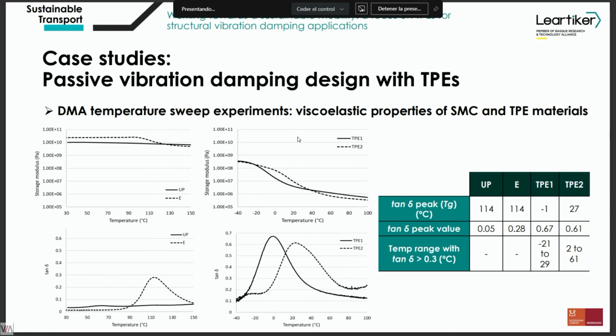On the other hand, if we compare the viscoelastic properties of the TPEs, we can see that the stiffness values are low, but the loss factor, tan delta, the vibration damping capability or energy dissipation that these materials give to the structure, is very high. If we compare these Avient grade TPE materials, we see that at room temperature the loss factor is higher than 0.3, which means a very, very good vibration damping capability. Also, if you take a look at the table, the range with a loss factor higher than 0.3 for these TPE materials can be very wide. In the case of TPE2, it is very broad, from 2 to 61 degrees, so we can go higher than room temperature.